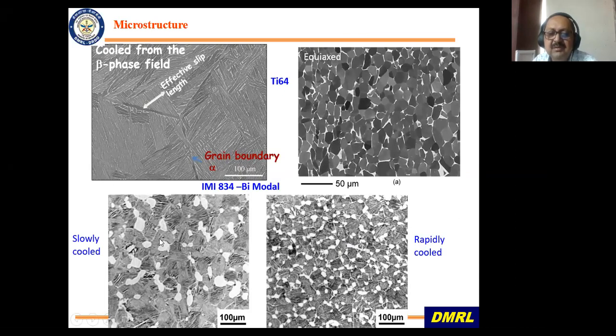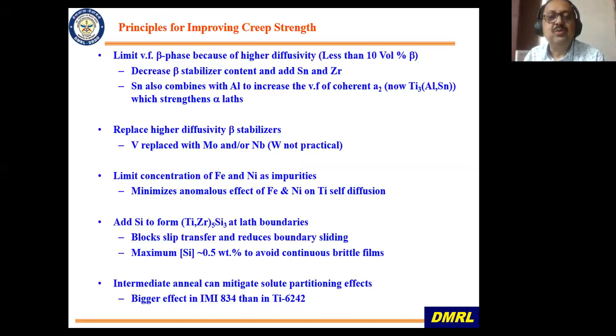Now, many times you would like to have a combination of good fatigue and good creep. So that is where this thing comes in. This gives a good combination of fatigue and creep properties. Fatigue because it restricts the grain size, the finer grain size, and the lamellar structure gives you good creep. So these kinds of processing are done for compressor blades, turbines, and all these kinds of things. Now I will go on to near alpha titanium alloys, which are a subcategory of alpha plus beta alloys.